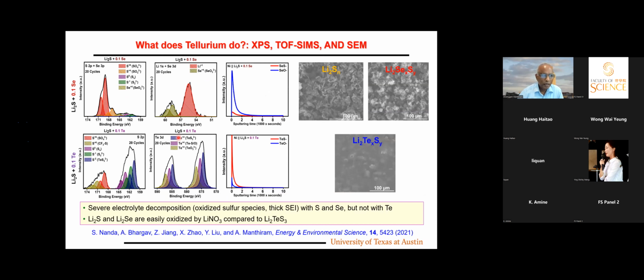So I've done a lot of XPS as well as ToF-SIMS. So I will give the data here. So what happens here is, if we have only sulfur and selenium with lithium nitrate added to the cell, the sulfide or polyselenosulfides moving from the cathode to the anode, they tend to get oxidized to oxidized species, sulfate containing species.